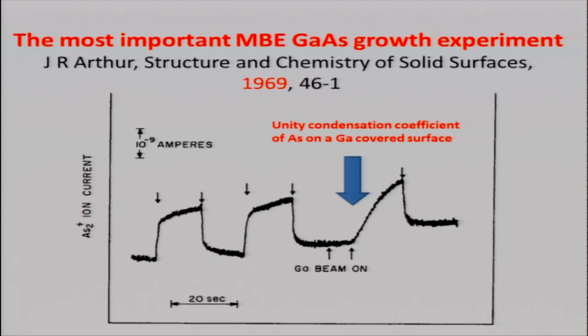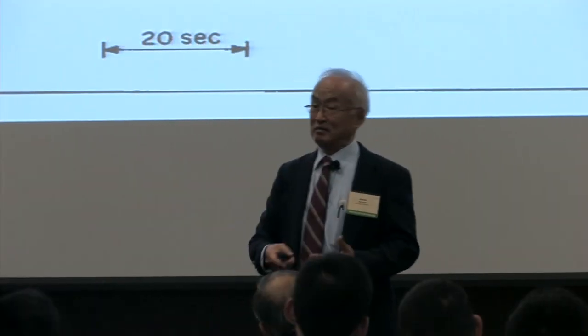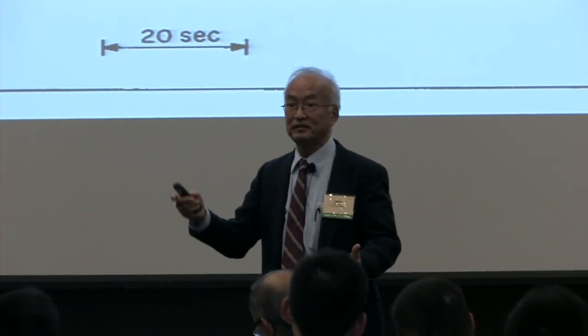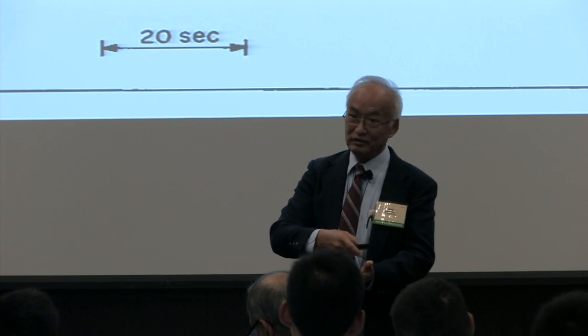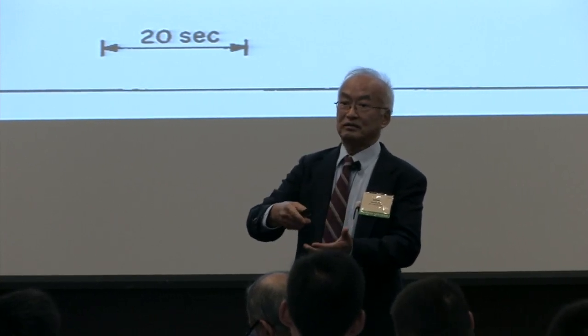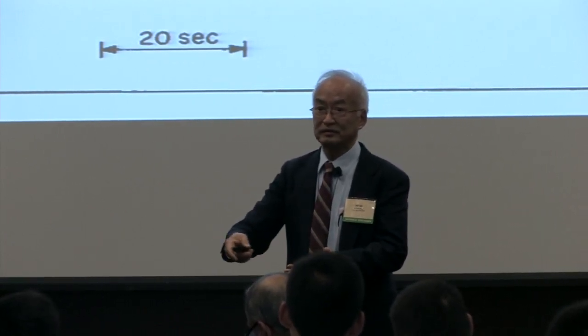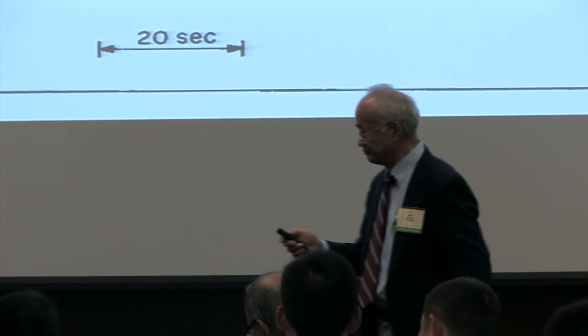So that's what made us know: you want to grow gallium arsenide? If you can plaster the surface with arsenic, it doesn't matter. The excess just bounces off the surface. So as long as you have enough arsenic and gallium on the surface, you grow gallium arsenide.